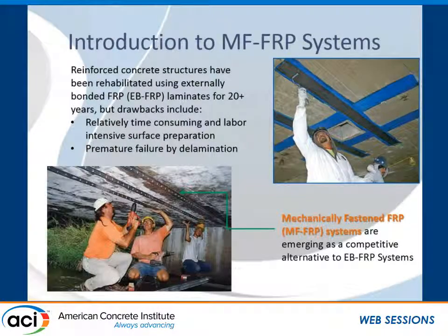So first of all, exactly what do we mean by a MF-FRP, or mechanically fastened fiber reinforced polymer system for strengthening? Typical FRP strengthening systems for concrete involve bonding the FRP to the concrete substrate using epoxy adhesives. While effective, the method requires the concrete surface to be properly prepared. The installation itself takes a substantial amount of time, in part because the epoxy needs time to cure, and special knowledge and skills are required for the actual installation. In addition, externally bonded repairs are susceptible to premature failure by delamination of the FRP. It's been a problem we've wrestled with.